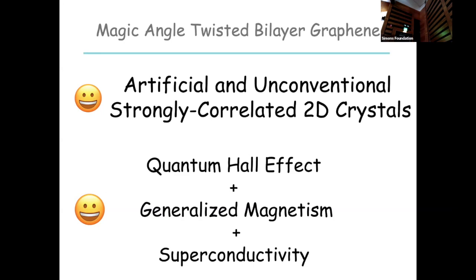Yeah, so one of the symmetries that's broken in these broken symmetry states is spin rotational invariance. So there is a spin Goldstone mode. Before we did these calculations, we weren't really certain that the spin wave would be below the interband particle hole continuum throughout the Brillouin zone. It is. But what was really surprising to us in these calculations is that the interband excitations between the occupied flat valence band and the empty flat conduction band, without any spin or valley flips, there is also a collective mode in that branch, which is below the particle hole continuum throughout the Brillouin zone, as though an electron sitting on that site in this insulating state is happy to be in the valence band or the conduction band. It only costs a little bit of energy to change the local state of the system.